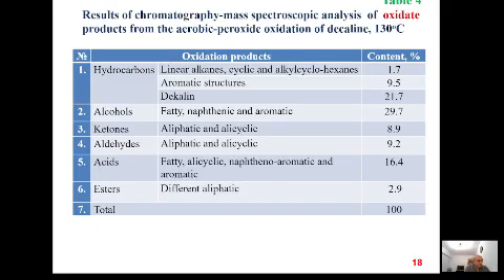This slide shows the results of chromato-mass spectroscopic analysis, which showed the formation of a wide range of different oxygen-containing compounds. These are unsubstituted, alkyl-substituted, and cyclic saturated, unsaturated, and aromatic hydrocarbons, as well as primary aliphatic, alicyclic, and aromatic alcohols, aliphatic and alicyclic ketones and aldehydes, aliphatic, alicyclic, aromatic, and oxy acids, and different aliphatic esters found in the oxidate.